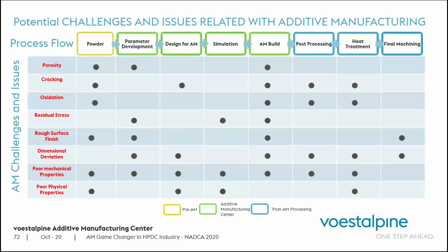it coming from? If you don't know, it could be from the powder, it could be from bad design, or it could be non-optimized building parameters. Something went wrong during the build, not controlling the oxygen content, as an example. Post-processing, maybe the heat treatment was wrong. So it's very hard to trace it back.